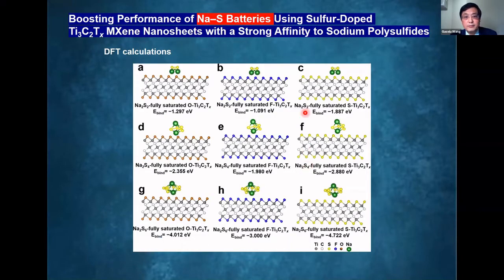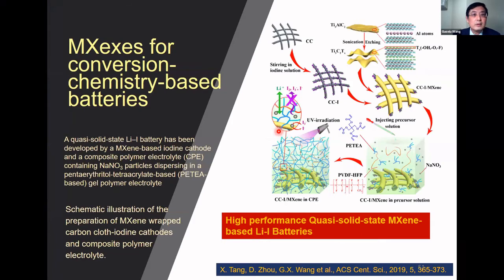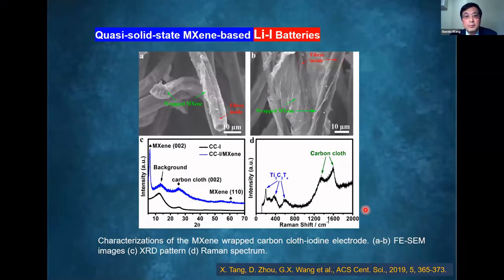And also we did the DFT calculations. We found that the sulfur-doped MXene shows much stronger absorption energy towards different kinds of sodium polysulfide. And then next, I will talk about MXenes for conversion chemistry-based batteries. So MXene can also be used for different kinds of conversion-based chemistry batteries. In this case, we construct quasi-solid-state MXene-based lithium iodine batteries. So the cathode materials we prepared, we wrap MXene because MXene is flexible. The individual MXene nanosheet is extremely flexible.